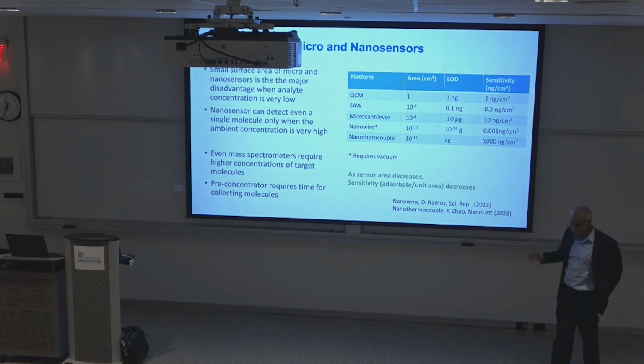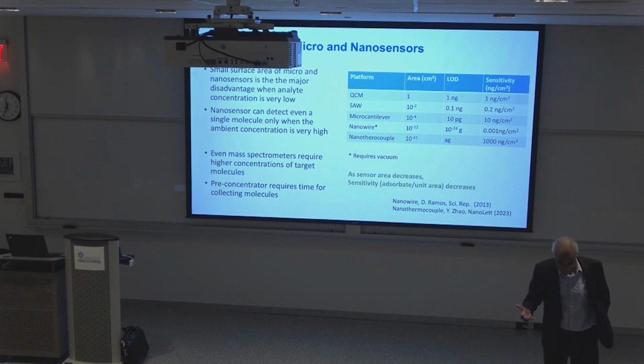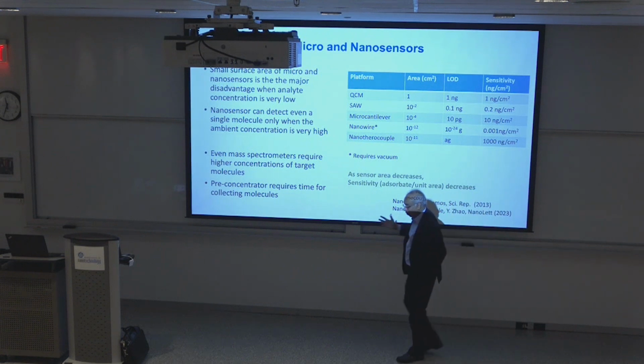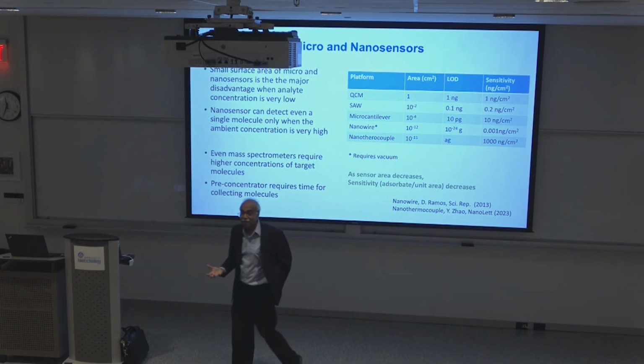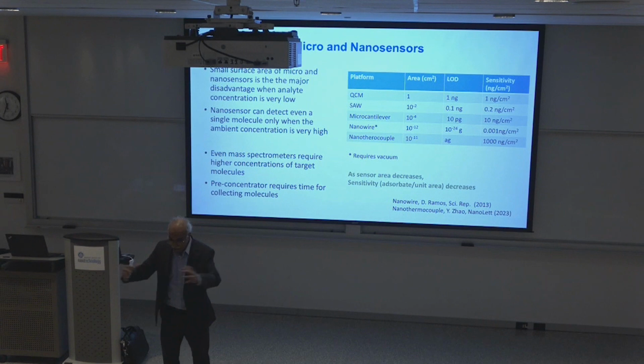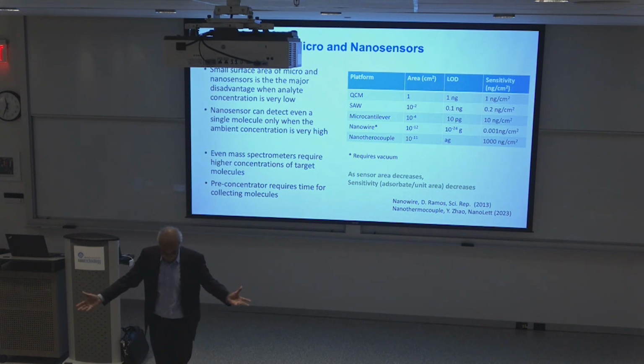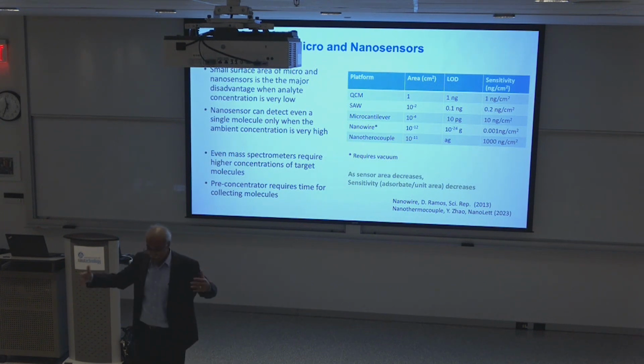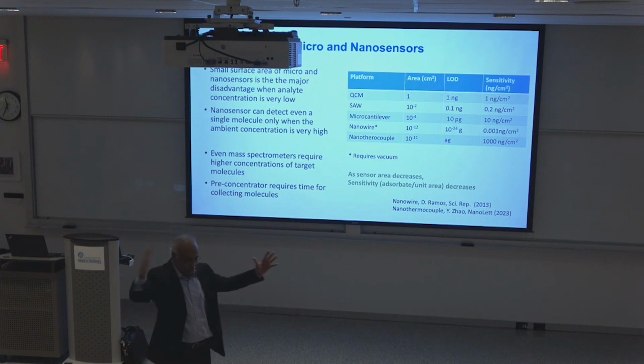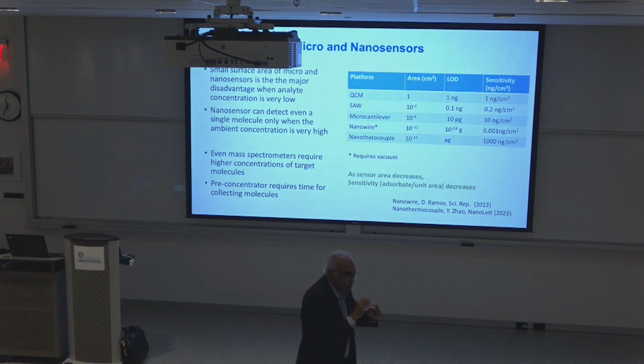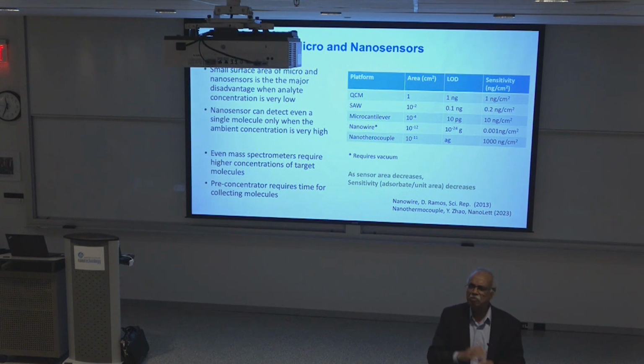As the sensor gets smaller and smaller, you need a lot more material to detect. That means you have to have lots of molecules around your nanosensor. A nanosensor can detect one molecule or a few molecules, but you have to have lots of them around. Otherwise, assuming parts per trillion or parts per billion molecules in the ambient, the chance of them adsorbing on that small functional area is very, very small. People use pre-concentrators to overcome this problem.